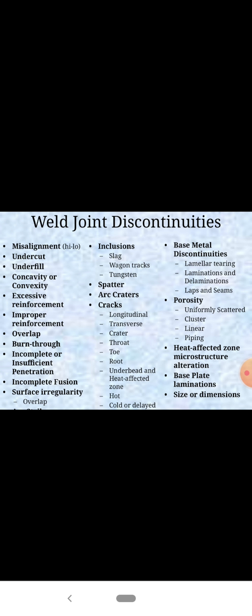So these are the kind of defects that arise in the various in-service conditions where the welding is to be performed. And then day by day, these kind of things have to be mentioned over here when they arise. So base metal discontinuity, porosity, heat affected zone, microstructure alteration, base plate lamination, size or the dimension. These porosities have various kinds of direction: uniformly scattered, cluster, linear, piping, and so on. So these defects are basically relating to these.